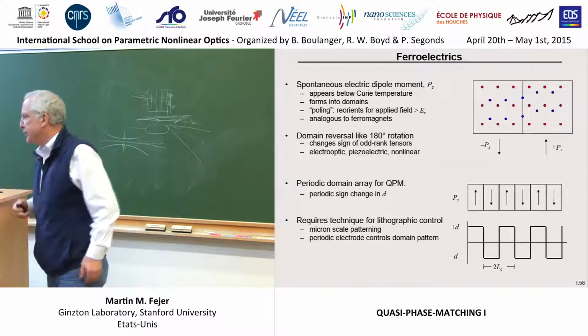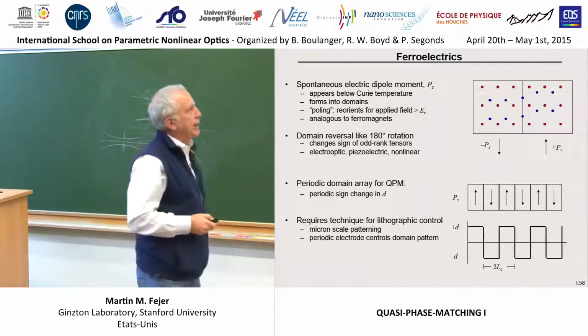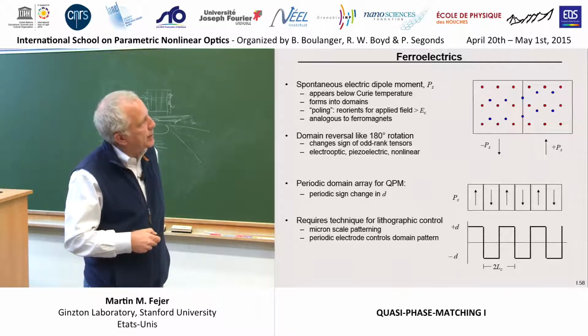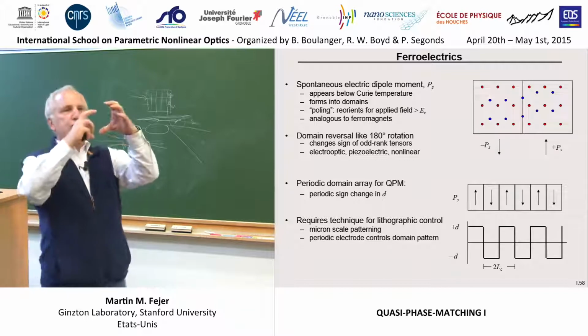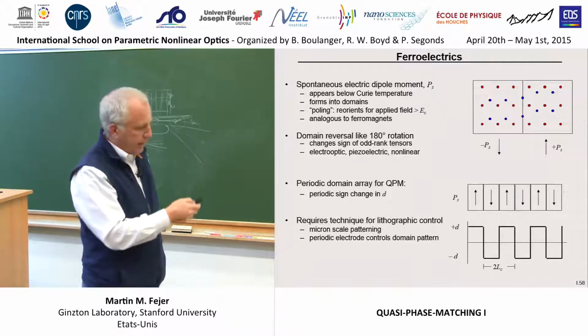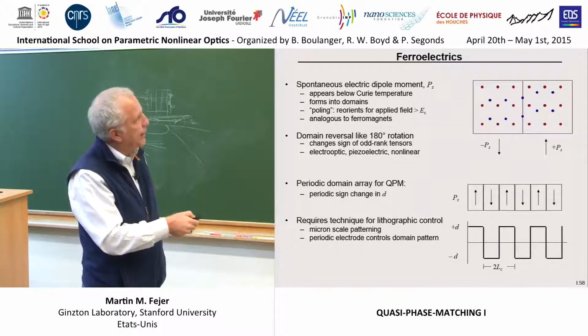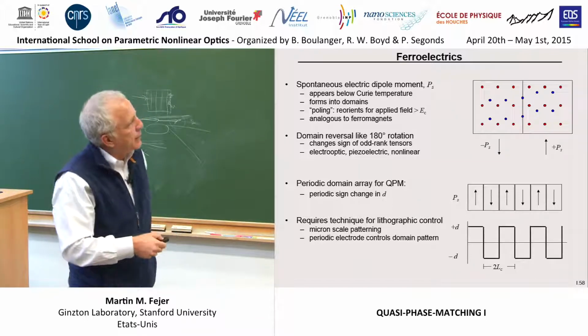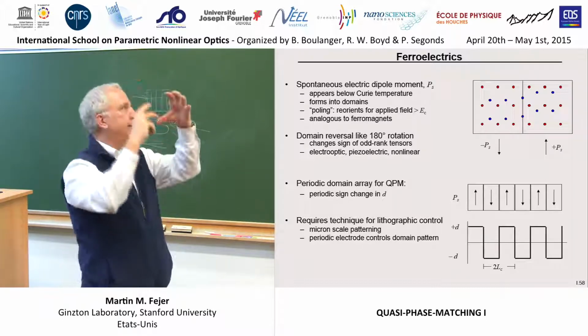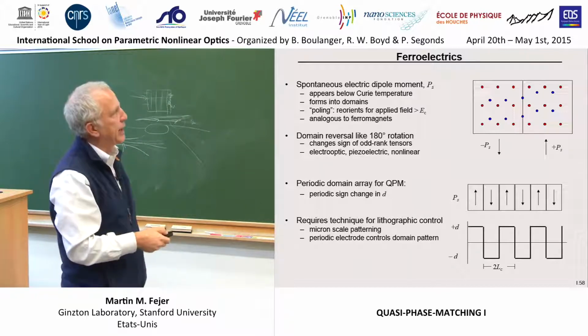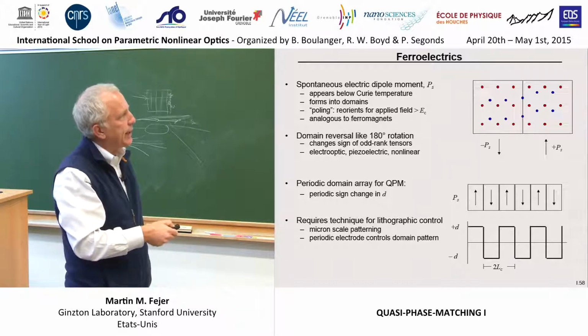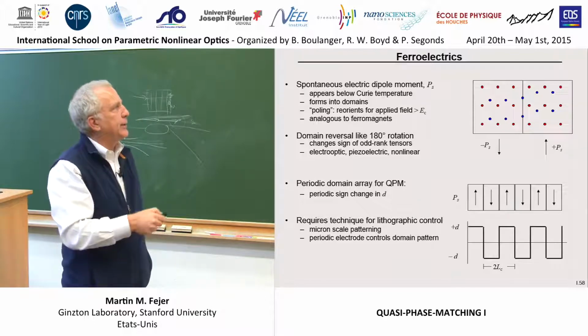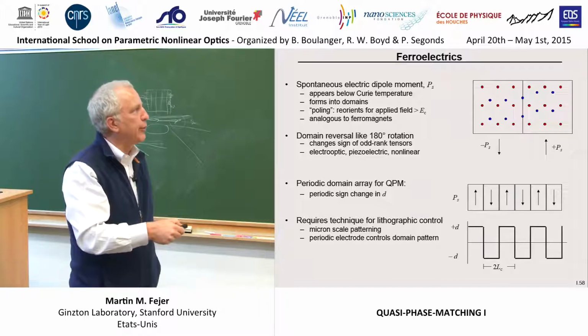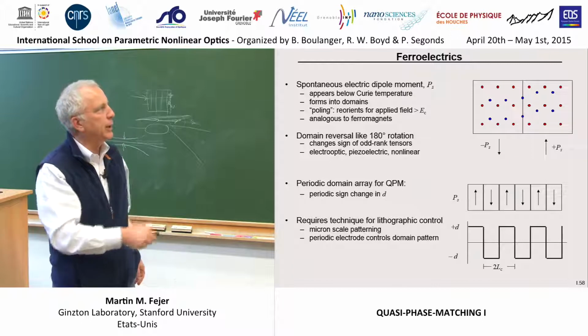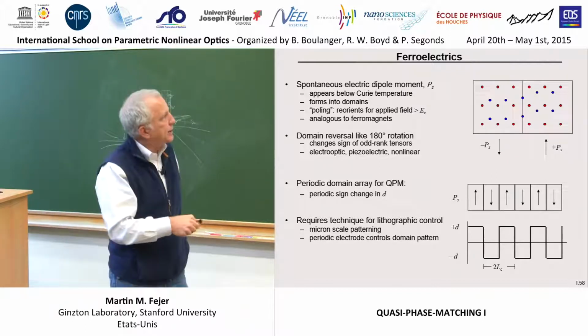So it never hurts. So a ferroelectric most simply can be visualized as a material in which there are sublattices of positive ions, these red dots, and negative ions, which are these blue dots. And if you shift the center of charge of the red and the blue here, the positive and the negative, there will be a net dipole moment in this region pointing, say, down. And on the other side, if the positive sublattice shifts the other way compared to the negative one, up instead of down, then you'll have a dipole moment in each unit cell again, and it will be of the opposite sign as you had over here. And a region of one set of dipole moments is separated from a region of the opposite sign by a domain wall. That's this line here.